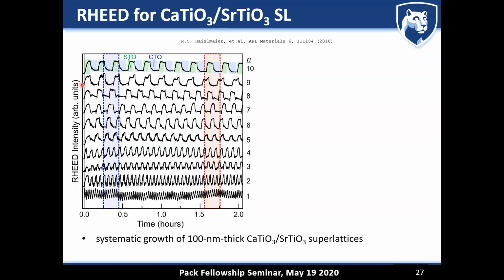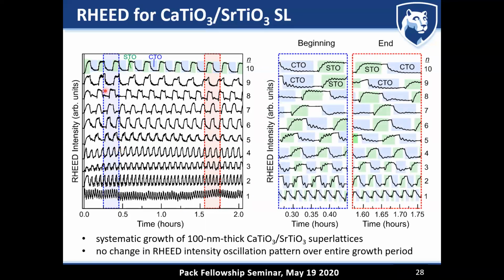And what I'm showing you here is the time-dependent RHEED intensity oscillations. That looks relatively unspectacular. However, when you're zooming in, you can see that, for example, when we're discussing the n equals 10 superlattice, where you have 10 layers of calcium titanate followed by 10 layers of strontium titanate, you can actually see in every growth period these oscillations in RHEED. And you can literally count how many layers we were putting down to then rest and then put 10 layers of strontium titanate down.